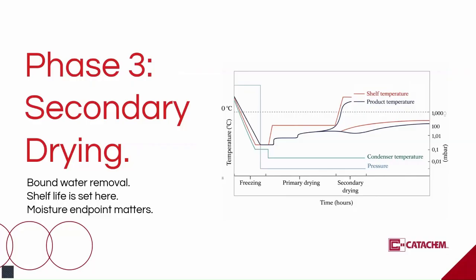Secondary drying removes bound water, the water that didn't leave as sublimated ice, but is attached at the molecular level to the formulation matrix. This phase can be the difference between a product stable for 12 months and a product stable for 24 months or more. It is also the phase where the tendency and easy route is to run a generic secondary dry phase of a basic recipe. This can be dangerous, and it is where value can quietly leak out.